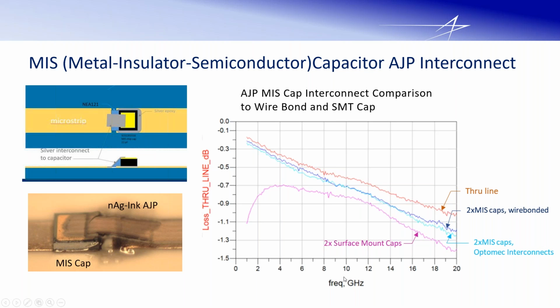So here shows an insertion loss curve, up to 20 gigahertz, and the typical surface mount that probably a lot of you use, with the end terminations and the multi-layer ceramic, you can see the insertion loss. You're up at 20 gigahertz, and you're at minus 1.4. Now, using the MIS caps with the printed connection versus the wire bond, here it's comparable to the wire bond. It has a smaller footprint than the wire bond, but comparable performance. And here's a picture of it.